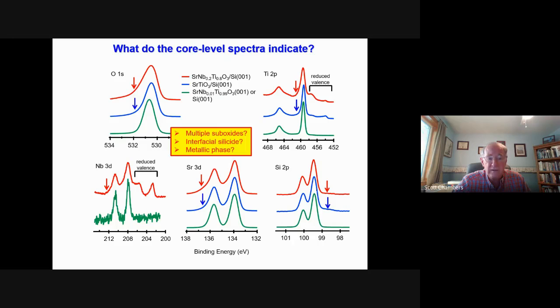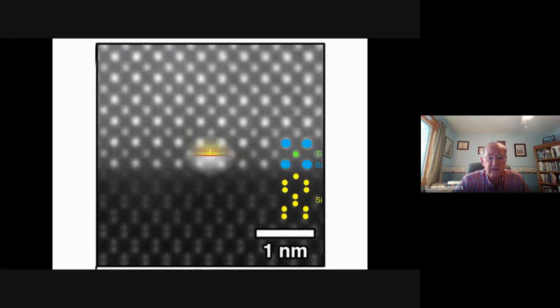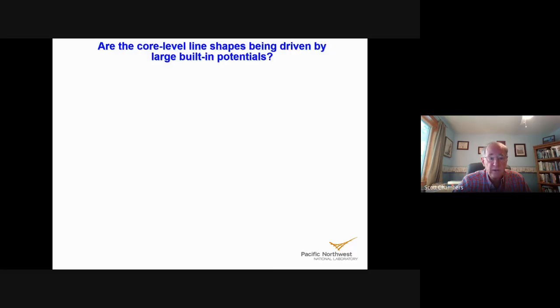But that's not at all what the material is. The material is, by all measures, X-ray diffraction, TEM, everything you can do, a very high quality epitaxial film that makes an atomically abrupt crystalline interface to the silicon. So what in the heck is going on? Well, we finally asked the question, could these weird core level line shapes be indicative of large built-in potentials that have something to do with the hole gas formation?